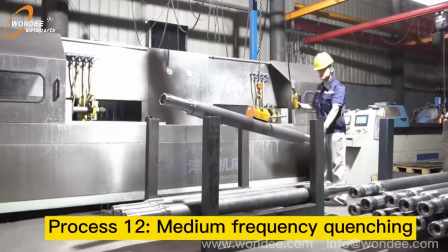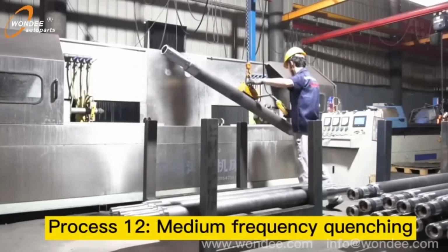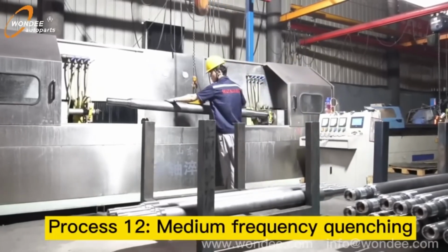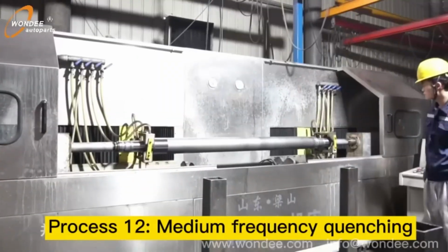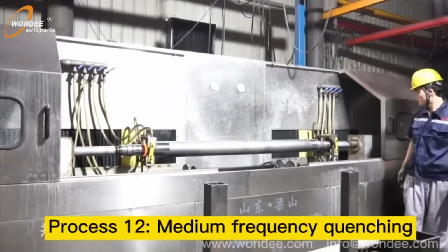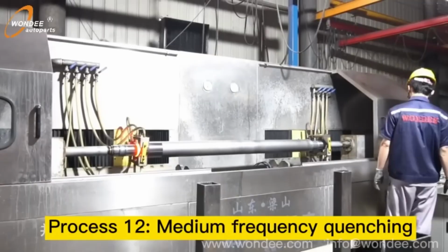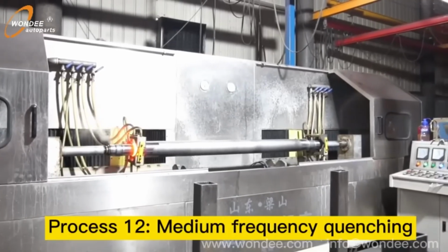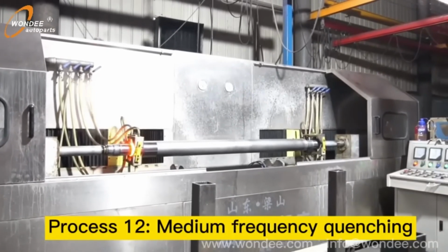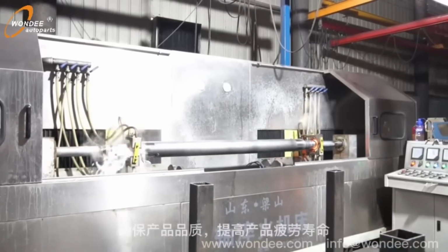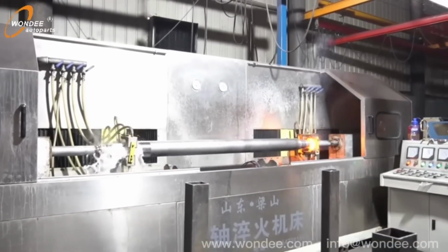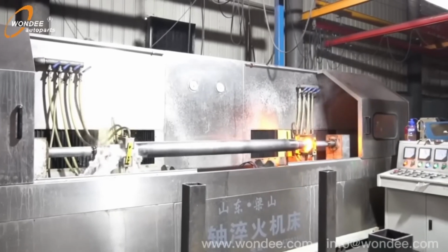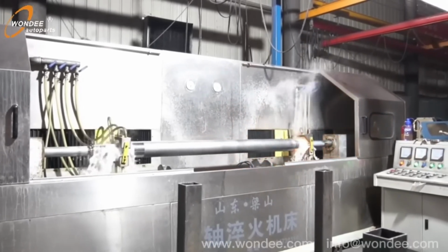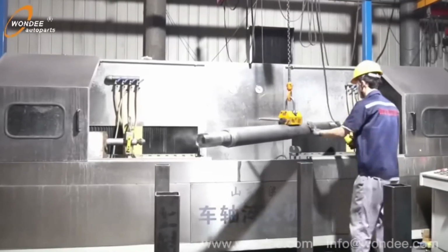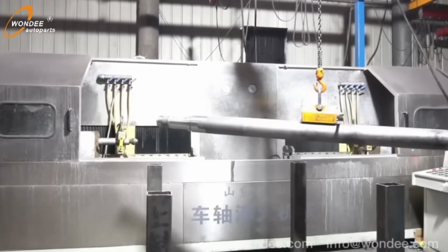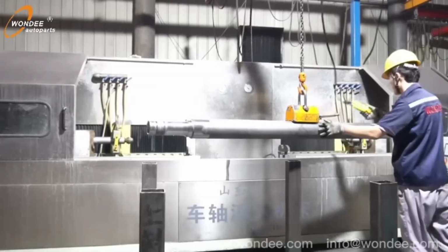Medium-frequency quenching is an induction hardening process used to increase surface hardness and wear resistance on critical axle areas like bearing seats and spindles. An induction coil generates an alternating magnetic field at medium frequencies, typically 1 to 10 kHz, rapidly heating the steel surface to temperatures around 850 to 950 degrees Celsius, while leaving the core cooler and tough. Once heated, the surface is immediately quenched using water or polymer solutions, transforming the steel's microstructure into hard martensite.